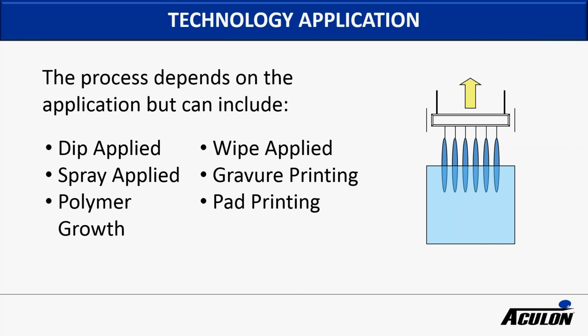One of the great things about our technology is it's easy to apply. All of our chemistries are either solvent-borne, or 95% of them are solvent. There are some that are aqueous, but they're all carried by a solvent, so they can be dip applied, sprayed, wiped. We've commercialized some in gravure printing, where you're doing a roll-to-roll process. We've also formulated our chemistry into inks that can be pad printed, and then we also have this polymer growth technology. So most of the time, very low capital costs to get set up, and the process is simple.